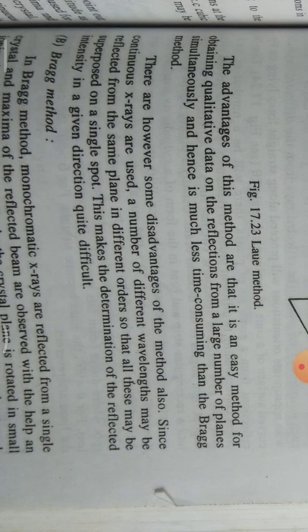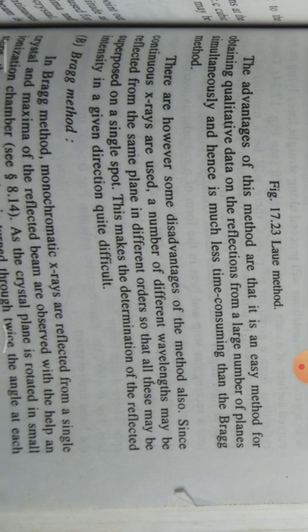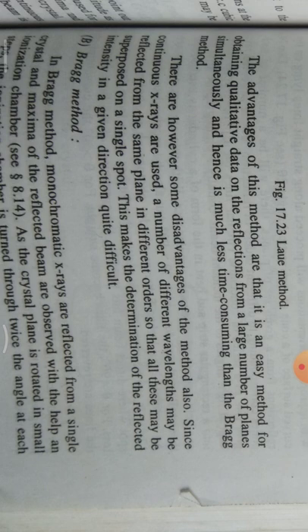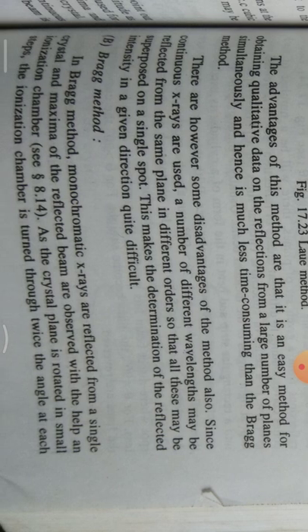Next topic, the advantages of this method are that it is an easy method for obtaining qualitative data on the reflections from a large number of planes simultaneously, and hence is much less time consuming than the Bragg method. There are, however, some disadvantages of the method also. Since continuous X-rays are used, a number of different wavelengths may be reflected from the same planes in different orders, so that they may be superposed on a single spot. This makes the determination of the reflected intensity in a given direction quite difficult.